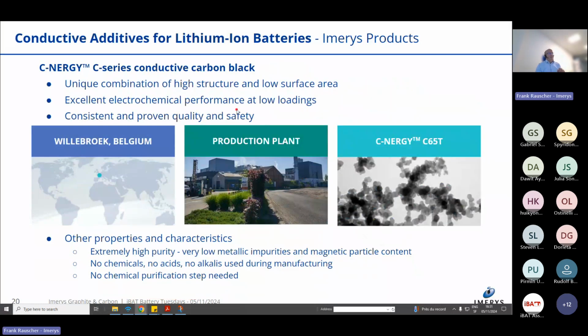The same is true for our carbon black. Here again, it's years of experience, that's not years, it's decades of experience that allows us to make a high purity conductive carbon black. That's a picture of our plant in Willebroek in Belgium. Unique combination of high structure and low surface area. That's why Super P Li and C65T are the most sold conductive carbon blacks in the lithium-ion battery industry. Good electrochemical performance at low loadings. This is what you are looking for. You don't want to add a lot of your conductive additives. You would like to have good performance at low loadings.